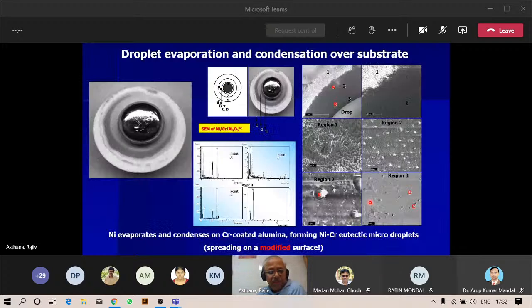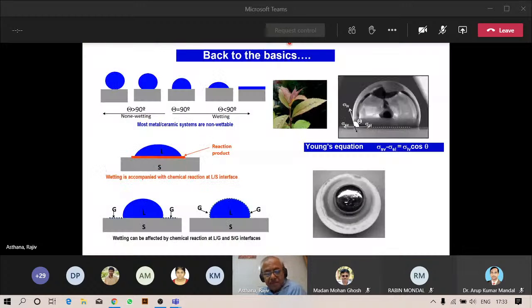And when we did the wetting test, what we found was that the evaporation and condensation of nickel ahead of the spreading droplet could modify the surface. So the droplet is spreading on a previously modified interface. In this particular case, we saw nickel chrome eutectic micro droplets forming on the surface of this alumina substrate. So these kind of challenges do not occur in low temperature systems or non-reactive systems, but they're unique to high temperature systems like molten metals and ceramic materials.